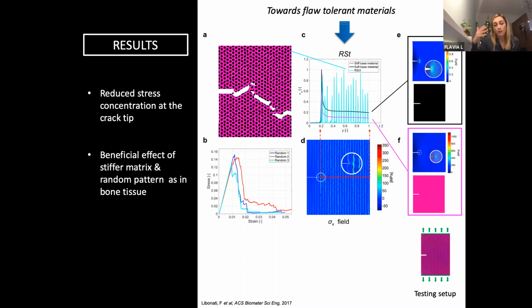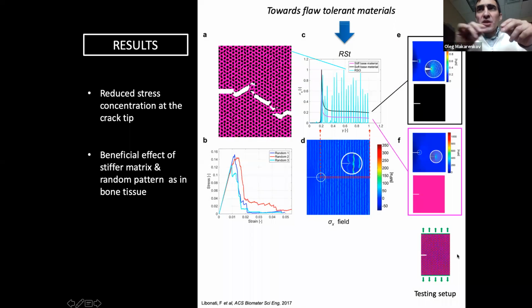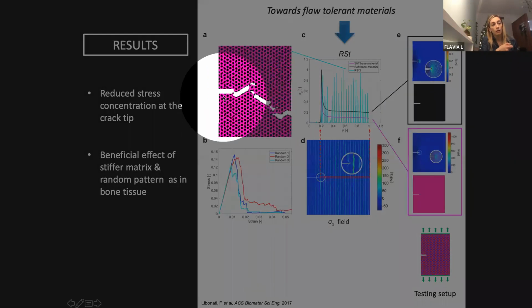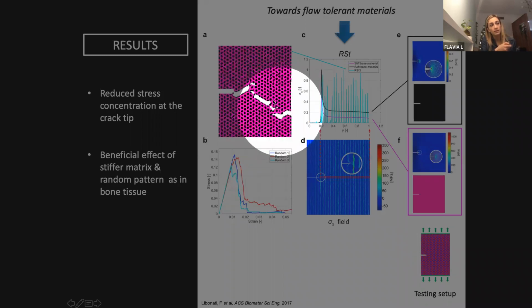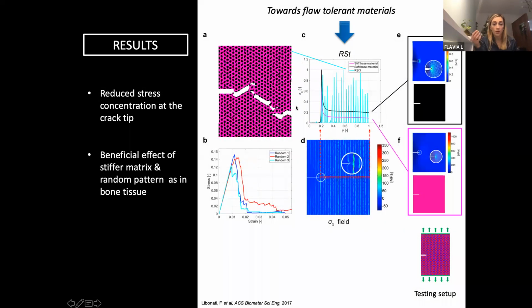So time by time you dissipate the energy, which means that you don't get an immediate breakage, a brittle failure as you can get in homogeneous material. You try to distribute cracks. The material doesn't fail by the main crack propagation. The crack starts propagating, but then the material starts failing somewhere else. So you don't have the main big crack, which is of course energetically favored in terms of dissipating the energy.